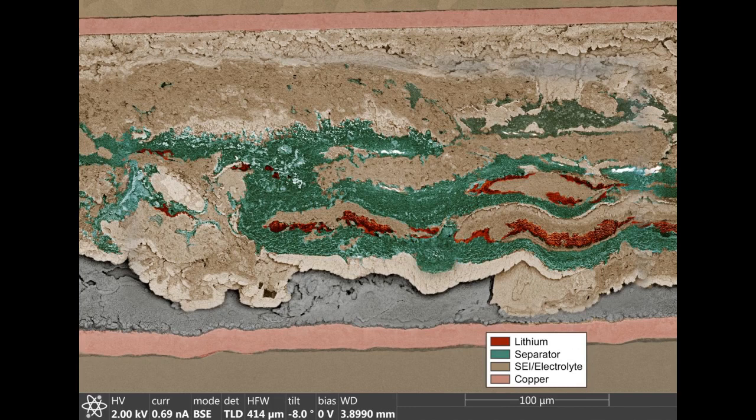The researchers used a microscope that has a laser to mill through a battery's outer casing. They paired it with a sample holder that keeps the cell's liquid electrolyte frozen at temperatures between minus 148 and minus 184 degrees Fahrenheit. The laser creates an opening just large enough for a narrow electron beam to enter and bounce back onto a detector, delivering a high-resolution image of the battery's internal cross-section with enough detail to distinguish the different materials.